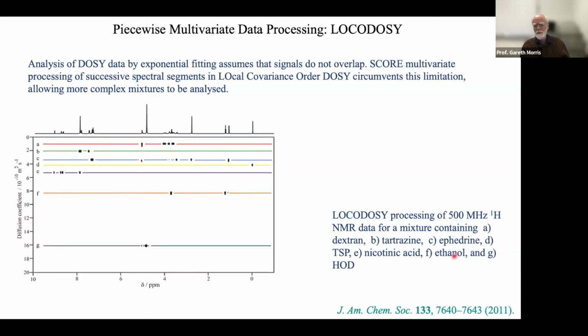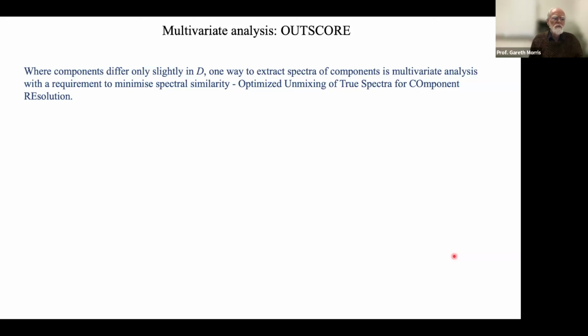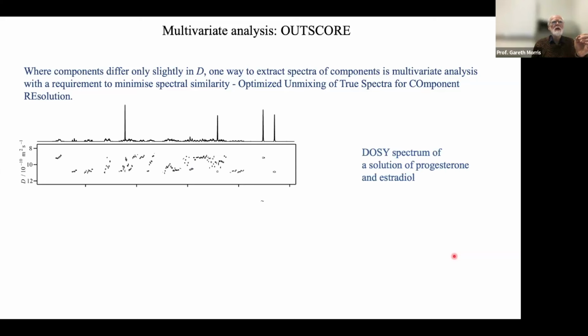Is there anything else we can do to separate spectra with multivariate analysis? Occasionally we have a problem where we have two very similar species giving us very similar spectra, but we do at least know that we've only got two species there. Something that we can do to increase the chances of separating them is to say, well, not only do we want the best fit in a least squares sense, but since we know that our spectra have small differences, let's try to get a compromise best fit, which is pretty good at minimizing residuals and also pretty good at giving different spectra.